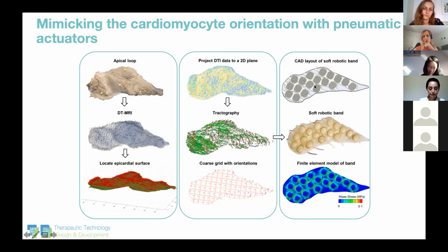You can see here, obviously, we don't get anything close to the resolution of the cardiac fibers themselves, and that's an ongoing work where we're trying to get higher resolution soft actuators into the band. But what we show here is they're called flat pleated pneumatic artificial muscles, and they're made from 2 layers of silicone, and sandwiched in between the silicone layers you have paper structures that are inextensible. And then in between the paper layers you have PVA, which is a dissolvable structure, so you're left with a bladder basically in between the paper and the silicone layers. And when you pressurize that, as you can see here, almost kind of like bubble wrap, you get radial expansion of these little bubbles, but also linear contraction.